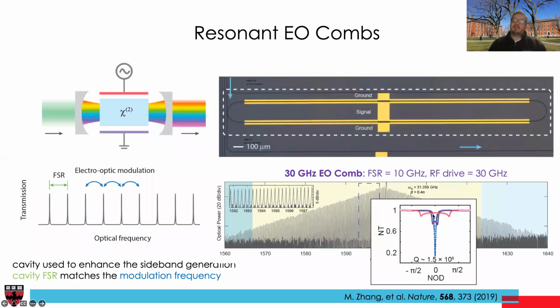So now, what happens when you turn RF on? RF couples nearby resonances. So essentially, if I put light in this resonance with RF on, now the photon can jump to this resonance, can jump to that resonance. Effectively, I'm using an additional loss channel for the resonator, which means the resonator immediately becomes undercoupled. And the more RF I apply, the more loss I have, the more undercoupled it gets. So with strong RF, I have this red line. So there's this trade-off. I want to apply a lot of RF to get a broad comb, but as I apply a lot of RF, no light goes in.